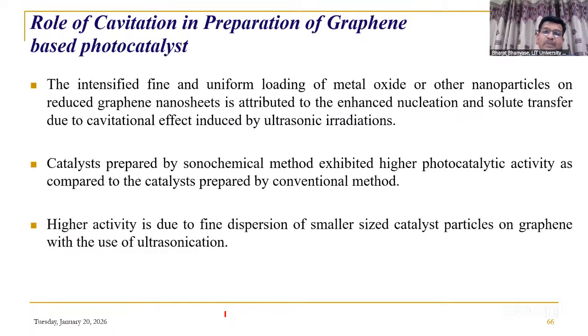What is the role in the preparation of graphene based photocatalyst here? We observe intensified, fine and uniform loading of metal oxide and other nanoparticles on the reduced graphene oxide, which is attributed to enhanced nucleation and solute transfer rate because of cavitation generated due to ultrasound use. Catalyst prepared by sonochemical method has higher photocatalytic activity compared to the photocatalyst prepared with conventional method, because of more active sites and uniform loading of these nanoparticles on the RGO sheet.